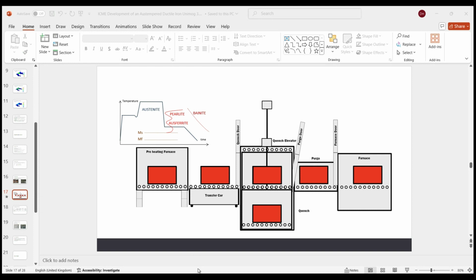And the parts go into the quench. In our smaller furnaces, we have 50 tons of liquid salt, which is agitated using impellers. The agitation moves the salt around the castings to get an even quench throughout the parts. Then once again they're soaked in that salt for the set period of time, depending on the temperature we're using, and they come out. We let the salt drain off, and then we wash the salt off.